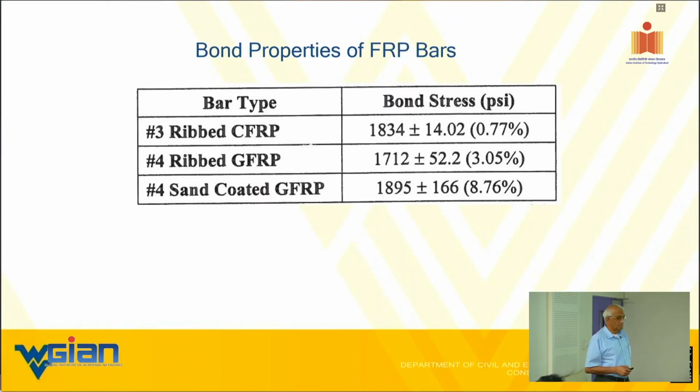But on the steel surface, we have lugs, formations. Oh yeah, lugs we call it. Comparatively, the sand coated has a projection size that is why you are getting a better bond, meaning you have a much higher contact area. That is what makes the bond better.